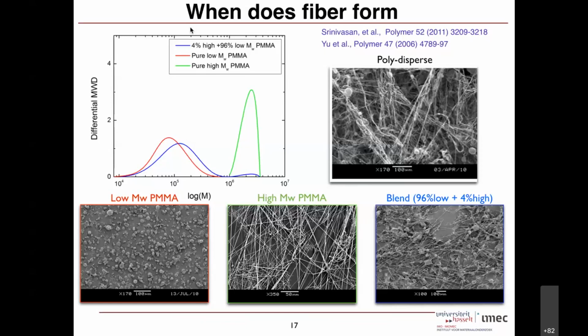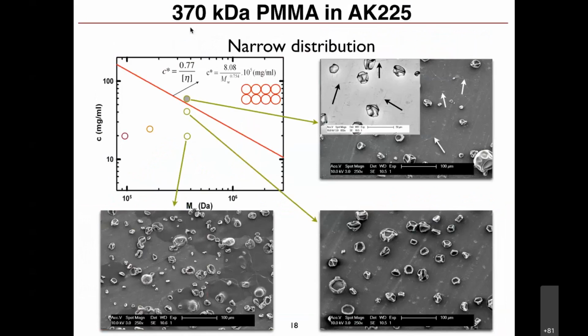So one trick you can do is this blue color. You use a lot of low molecular weight polymer, so your viscosity is less, like water. But add a very, very small amount of this high molecular weight polymer, which is the second peak in the blue. And then if you mix the two, you're going to get fibers. So that's the trick that we used. I'm going to show you a couple of images, right? How with electrospinning we can make fibers based on different molecular weights. So one is this 370. 370 is just a number, a methyl methacrylate polymer.